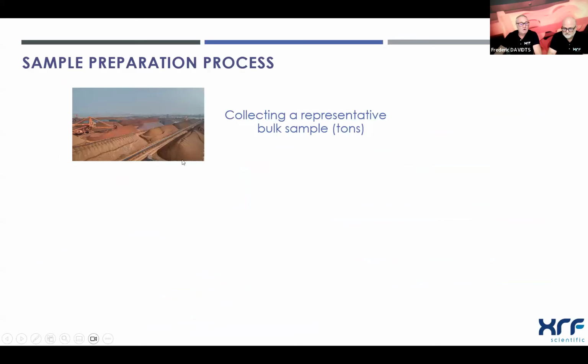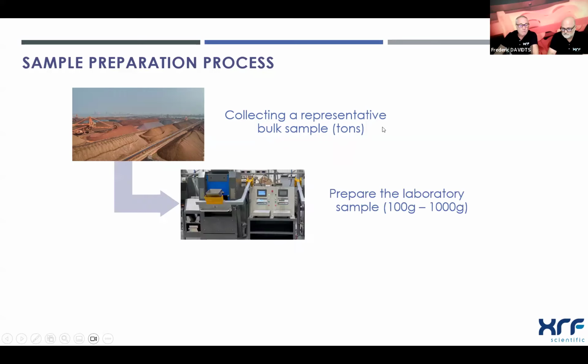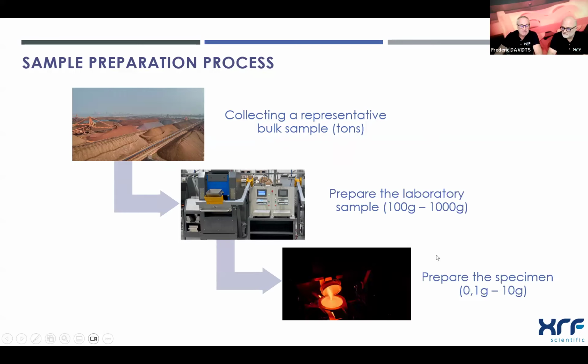The sample preparation process is very important. So first of all, we start with collecting a representative bulk sample. The bulk can be many tons of material, it can be ore, it can be oil, whatever your bulk sample is, we speak in general about tons. And from these tons of material, we want to prepare a representative sample for the laboratory, a sample that the laboratory people can use to make their final specimen that will be analyzed.